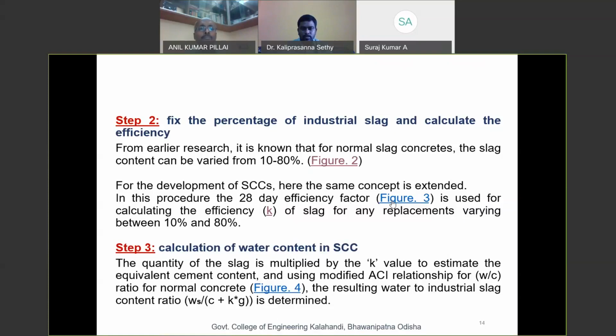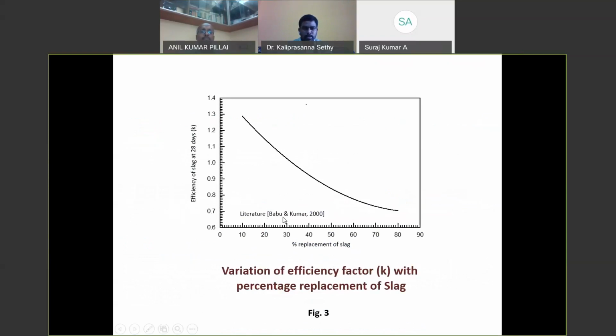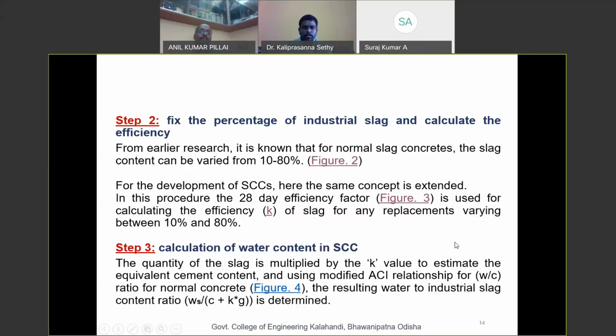So let me go to the slide. Okay, so 28-day efficiency factors. From this figure, which is also given by Babu and Kumar in the year 2000, you can see the curve plotted between replacement of slag and efficiency factor, that is K value. If we replace slag up to 80%, then the K factor value is somewhere around 0.7 or 0.71. With this value, we multiply the K factor with our slag percent to get the equivalent cement content in our total cementitious material.